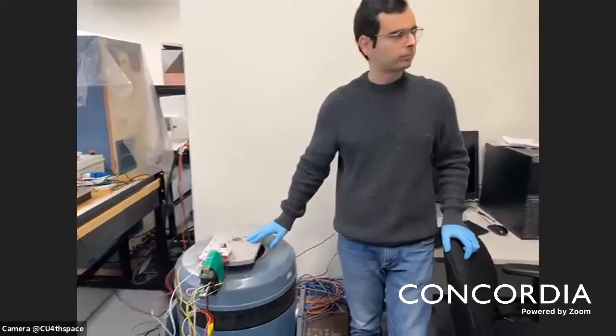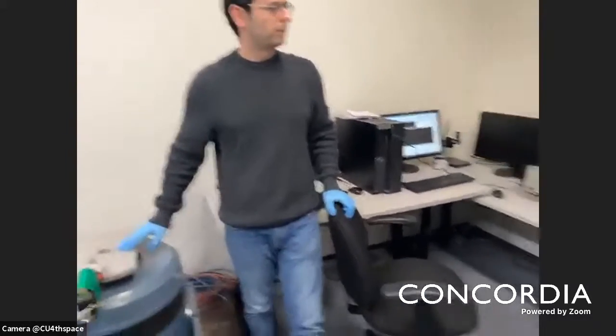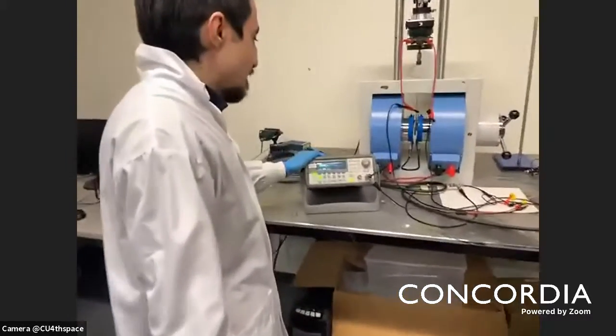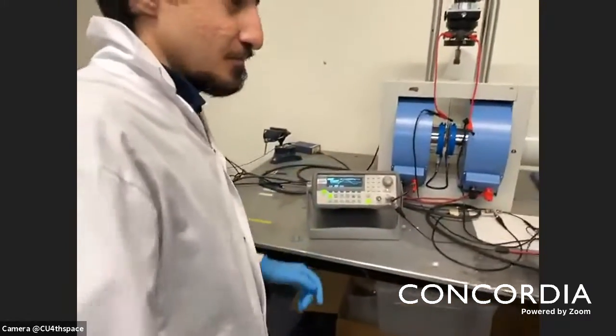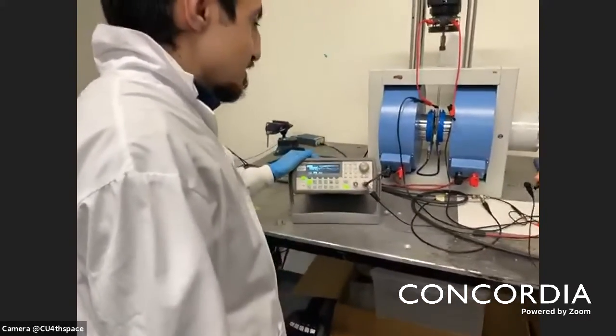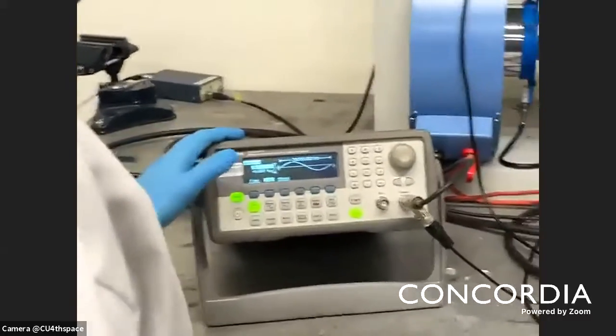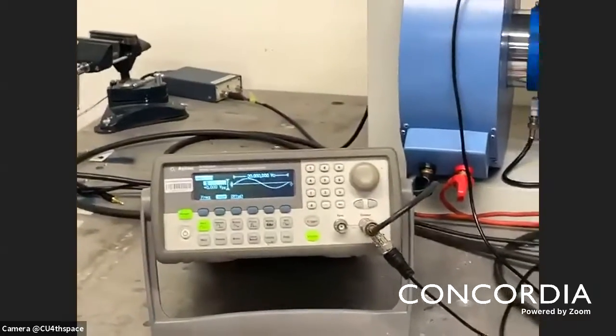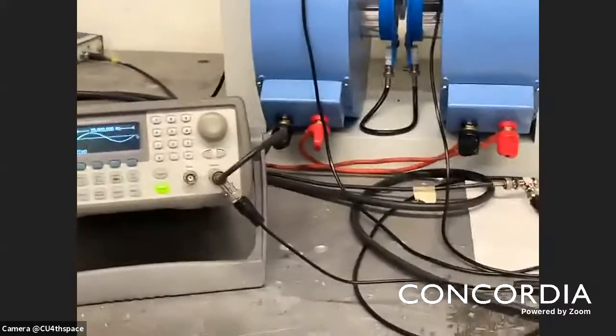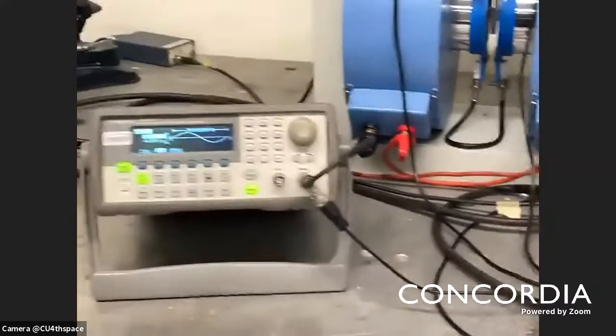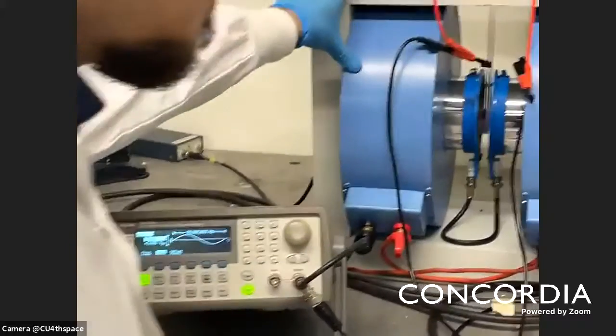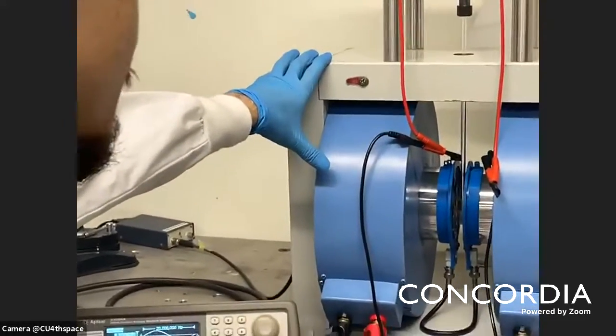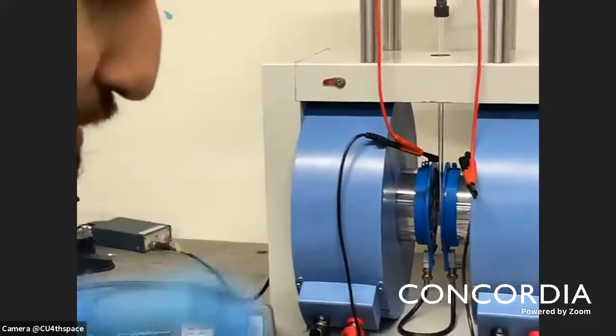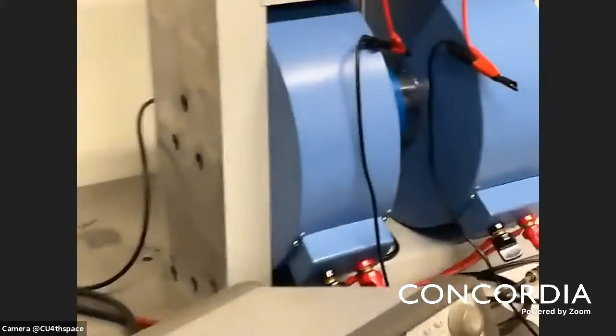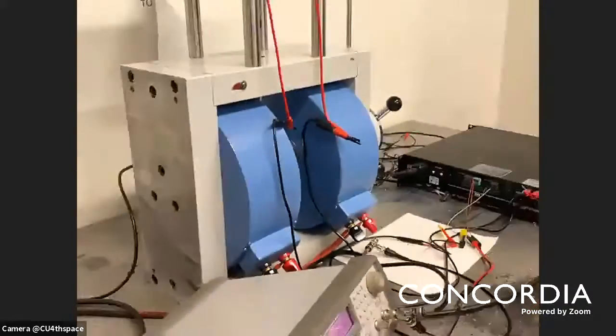I'll hold the microphone for now so we can go back and forth. Here is a vibrating sample magnetometer that I fabricated at Concordia University as part of my thesis. As I said, with that device we can measure the magnetic property of the elastomer that we fabricated. By using this device, we can measure the magnetic property of that elastomer, such as the magnetization, permeability, saturation level, and so on. If you would like, I can show you the